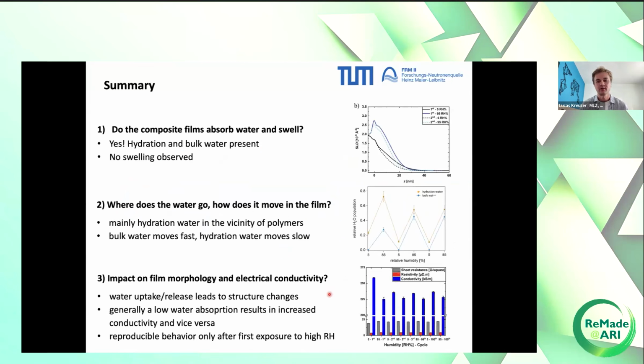And I also talked on the last two slides about the impact on the film morphology and the electrical conductivity. So a dewetting of the PEDOT:PSS in a humid state leads to a decrease in conductivity, and a rewetting in the dry state leads to an increase in conductivity. And the question now is, is there a certain sweet spot where we can have an optimized conductivity?